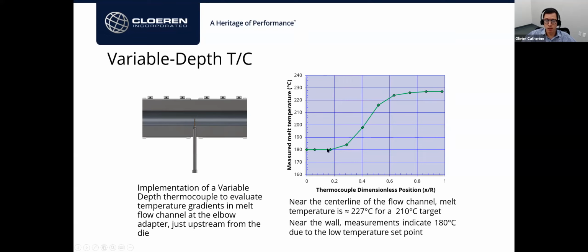But the cool thing is that we were able to determine that the melt temperature was higher than what they specified at 210. So 210 was really the target, but due to some poor control of melt temperature, this customer was basically trying to cool the melt in the melt pipe by setting the temperature set point much lower, at 180 C. So that's why you see initially near the wall 180 C, and then at the center of the pipe a much higher melt temperature than specified.